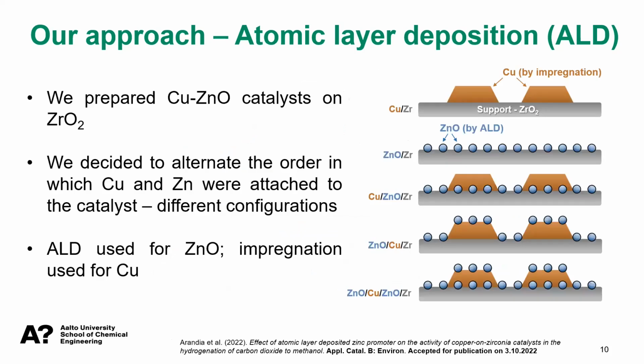So we decided to prepare copper zinc oxide catalyst on zirconia. We didn't investigate alumina; we decided to go with zirconia. And we decided to alternate the order in which copper and zinc were attached to the catalyst. So we prepared different configurations. We used atomic layer deposition for the zinc oxide and more conventional methods like impregnation for copper. So we prepared all the configurations that you see here.